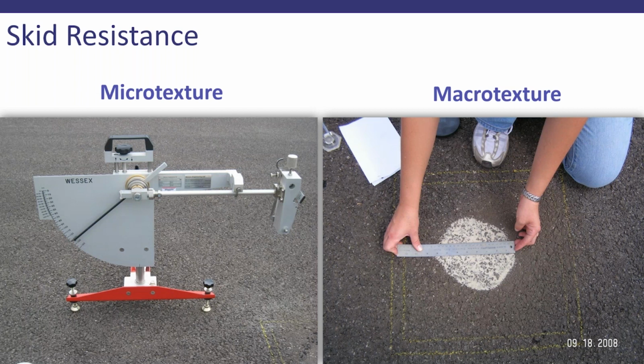So that really deals with the microtexture, which is kind of the grit and the grip of the aggregate particles themselves. Now the mix will have a macrotexture. There will be some little spaces and that bigger texture, which is why it's called macrotexture. But those are the spaces within the surface of that mix where water might be able to sit temporarily during a rainstorm to keep it from being right on the surface. If everything is super, super smooth, there's no reservoir area for that water, and so it's just going to come in contact with the tires. But if we do have a good amount of macrotexture, that water can live somewhere until it can run off and keep it from breaking the bond between the vehicle tire and the pavement surface.